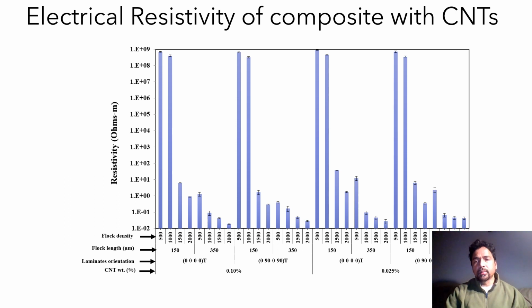This slide is very crowded, but it gives us the entire picture of the theoretical measurements we captured in this experimental study. In the horizontal axis, we have different flock densities of carbon fibers, and we have different fiber lengths. As I mentioned, we employed two different fiber lengths, 150 and 350, and two different laminate orientations: unidirectional, which is 0/0/0, and cross ply, which is 0/90/0/90. And then we also tried two different amounts of carbon nanotubes to see the influence of weight percent of carbon nanotubes on the results, which is 0.1% and 0.025%. These are very, very small quantities of carbon nanotubes.